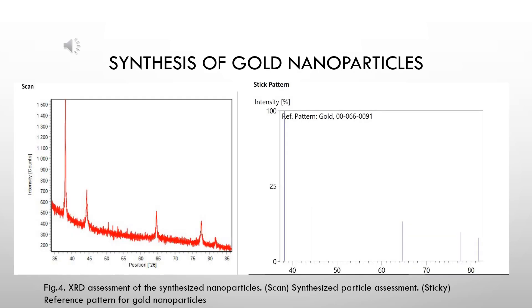After choosing the probes, we ran them through BLASTN and confirmed that our two probes were specific for the gene we targeted. Since our two probes were very suitable and could flank our gene, we then decided to synthesize gold nanoparticles using the citrate reduction method. Following the synthesis, we performed X-ray diffraction analysis of the synthesized nanoparticles and confirmed we had obtained gold nanoparticles, since our pattern was in line with the reference pattern for gold nanoparticles.